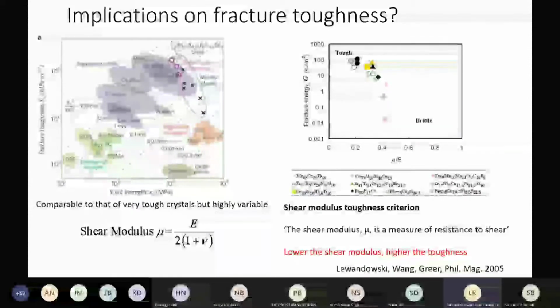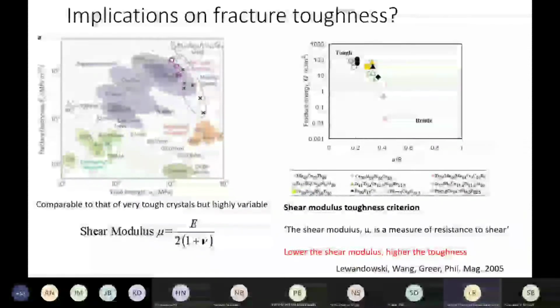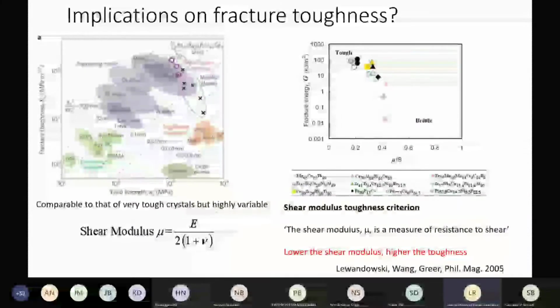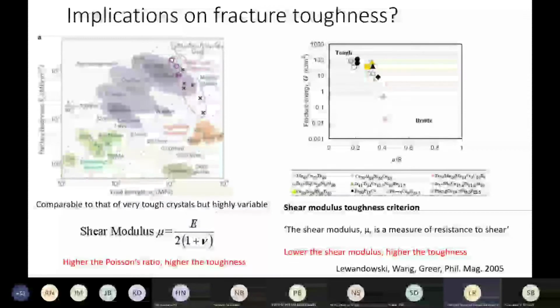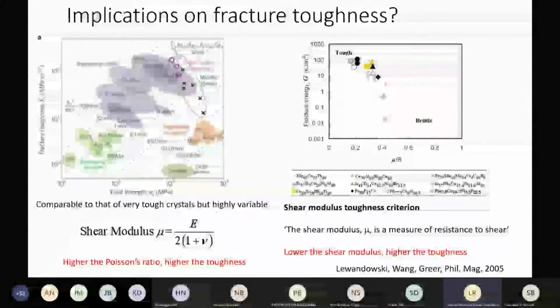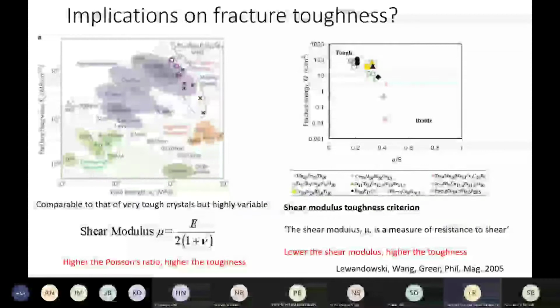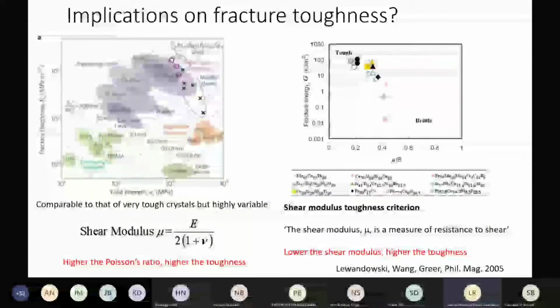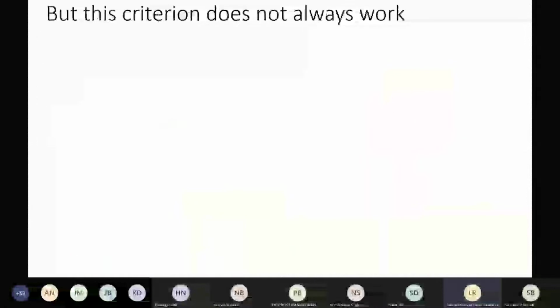And now they also modified the criterion further to say that your shear modulus is related to the Poisson's ratio, as in it is inversely proportional to the Poisson's ratio, and hence if you have a higher Poisson's ratio, you will have a higher toughness. And this became a sort of a benchmark for deciding which metallic glasses are going to be tough and which are not going to be.